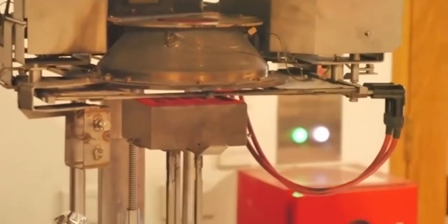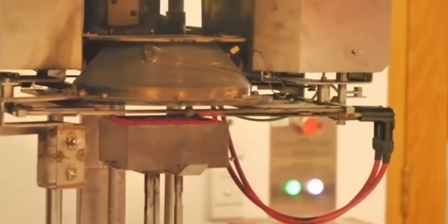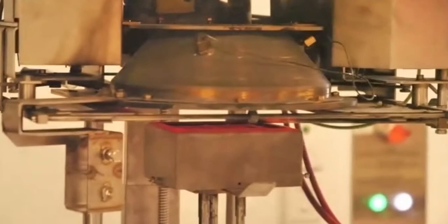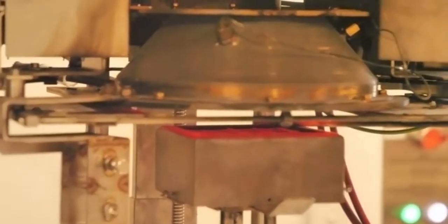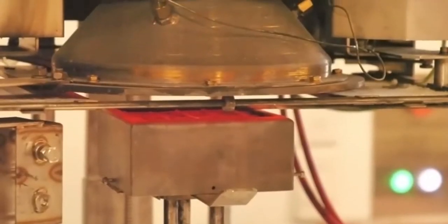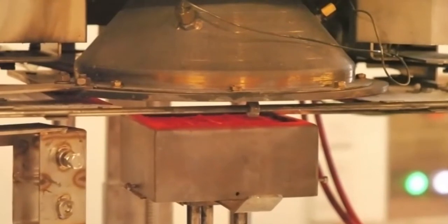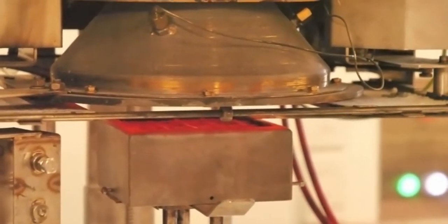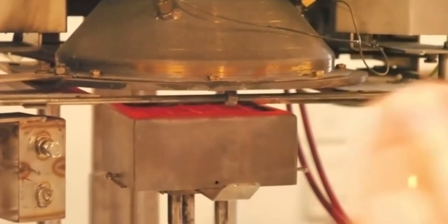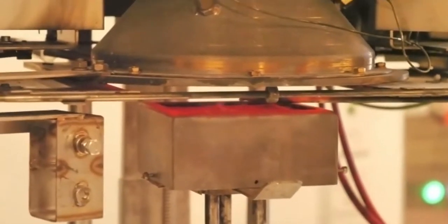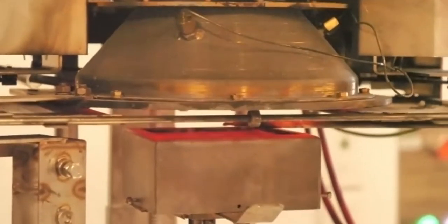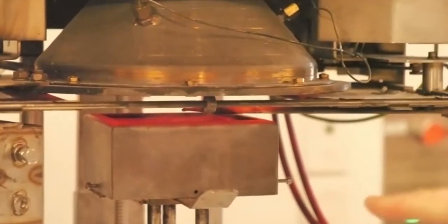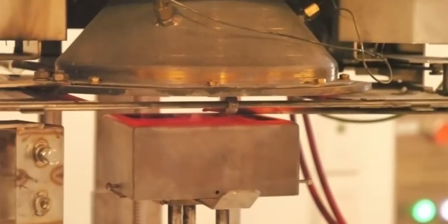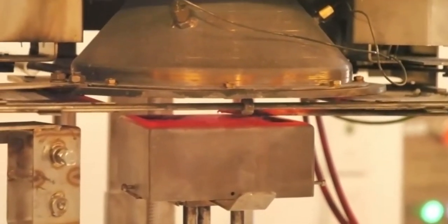Okay, so what we have now, if we look closely, is a material that is placed, a composite panel from a facade. That material is in this sample holder that, in case it melts, makes sure that we don't have dripping here. Now, what we are doing at the moment is exposing the surface to heat. And we see that the material starts to heat up at the surface.